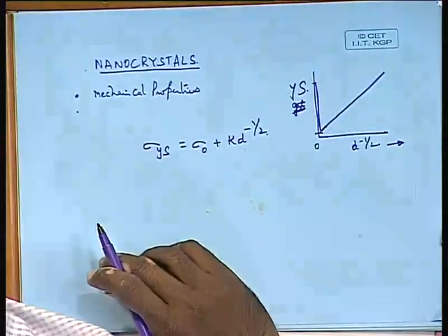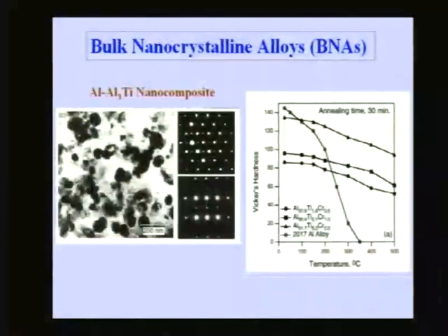That is what is called an FCC ordered structure, and if you subject such an ordered structure to diffraction, and look at these 2 diffraction patterns, you will clearly see there are faint spots in addition to the major spots.